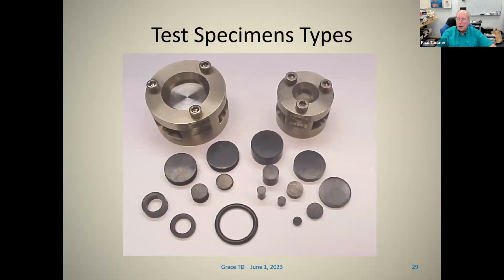In this case, when I was doing FKM testing, I showed that specimens with the same shape factor, which is a ratio of diameter to thickness to diameter, all had the same retained sealing force. Specimens with high shape factors, which were large diameter and small thickness, had poorer retention of sealing force, and the ones that were taller with smaller diameter had better retention. So it gives you some idea of the effect of shape and size on that.